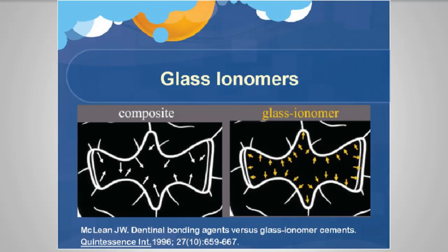The other very wonderful thing about glass ionomer-like materials is that they don't have polymerization shrinkage. They have an affinity for the overall tooth structure. They love it. And basically, when you restore in the proper manner with some moisture present, not underwater, but with some moisture, you don't want to desiccate the teeth when you're working with glass ionomer because it'll just suck all the moisture out of the dentinal tubules.